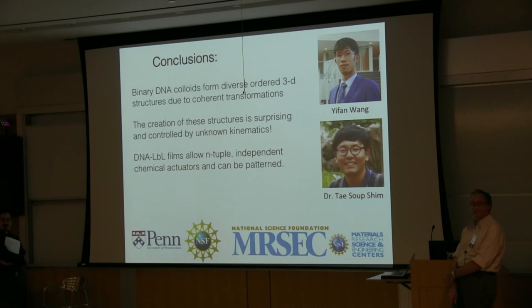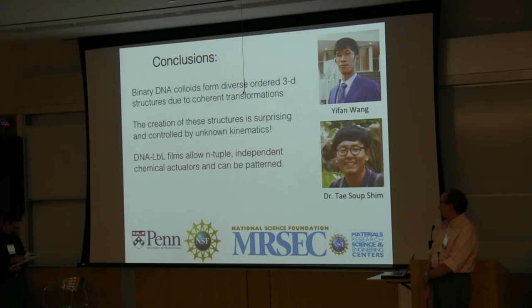Yes. Could you also use temperature for having the spreader come on and off instead of using? You know, we thought that would be easy, and it never really worked. Okay. And I think the reason why it didn't work is because we're simple-minded. Okay. The nice thing about that whole chemical reaction cycle with the strand exchange reaction is that the energies involved are way bigger than kT, so it kind of operates very mechanically. Like everything goes to completion, and then it goes to completion again. And then if you start actually going to places where things are happening by thermal excitation, it just sits in some middle state, you know, and just kind of continuously transforms or falls apart or does something more non-intuitive.